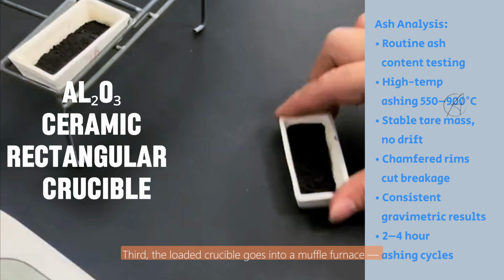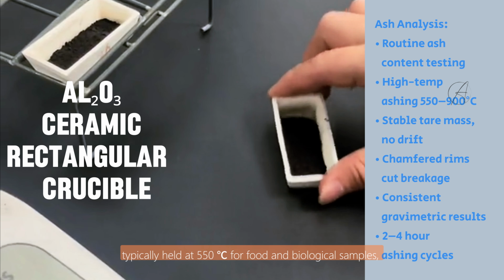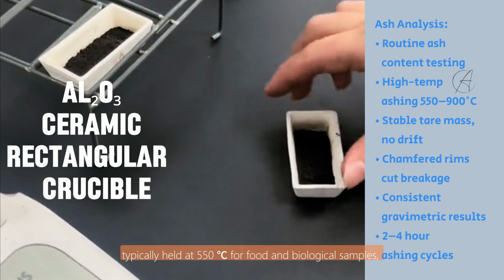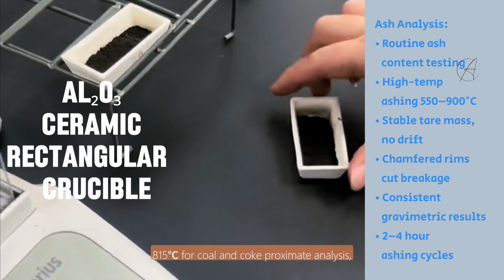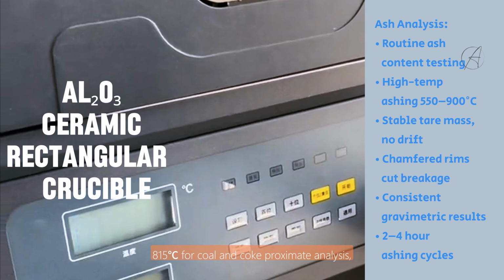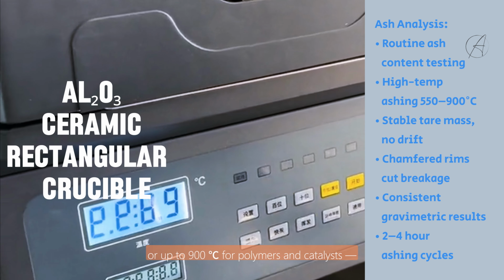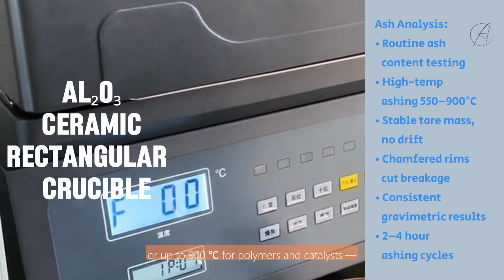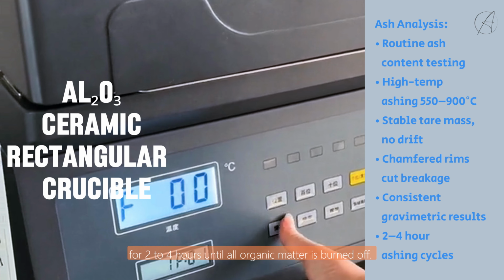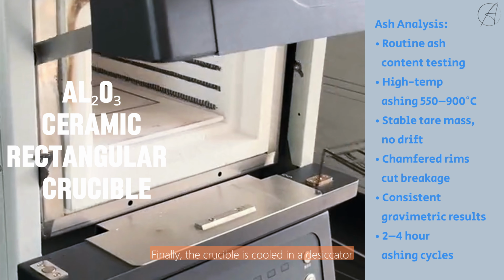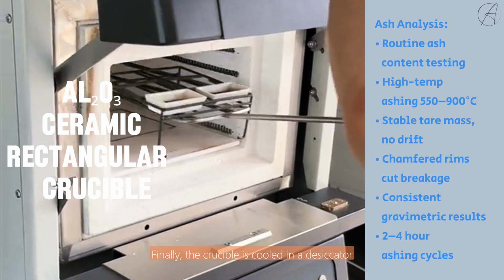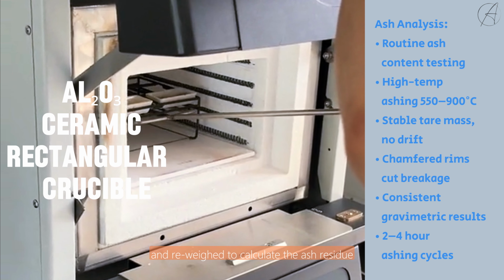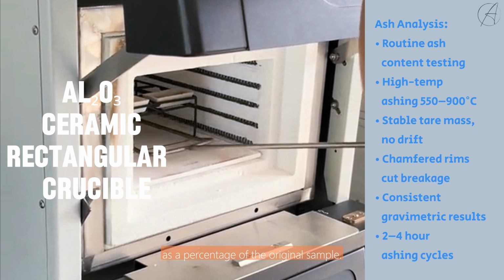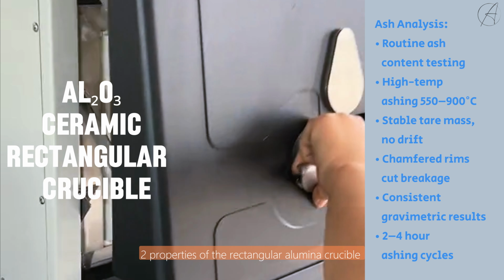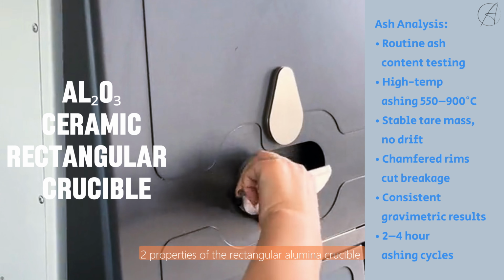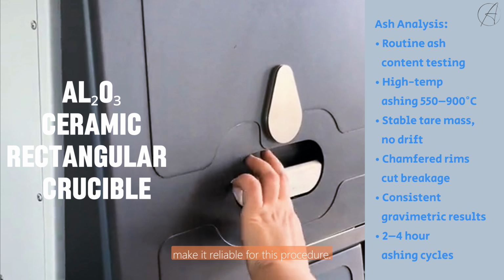Third, the loaded crucible goes into a muffle furnace typically held at 550 degrees Celsius for food and biological samples, 815 degrees for coal and coke proximate analysis, or up to 900 degrees for polymers and catalysts for 2 to 4 hours until all organic matter is burned off. Finally, the crucible is cooled in a desiccator and reweighed to calculate the ash residue as a percentage of the original sample. Two properties of the rectangular alumina crucible make it reliable for this procedure.